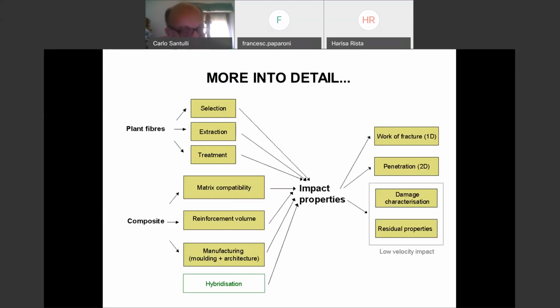residual properties, because, for example, you can impact samples and then you can cut slices, cut the central slice and have a tensile testing, and you can see that the tensile strength will be lower depending on the impact energy you applied, but it's important to know how much lower it is and how large is the variation of your post-impact residual property. In materials science, when we say residual properties, it means properties after damage or after the exposition to temperature or to humidity, etc. So residual, what remains.